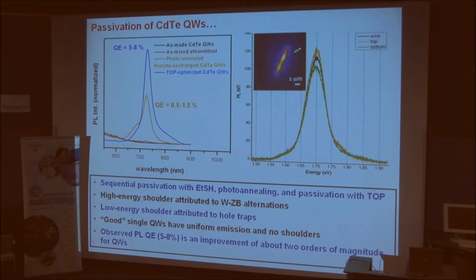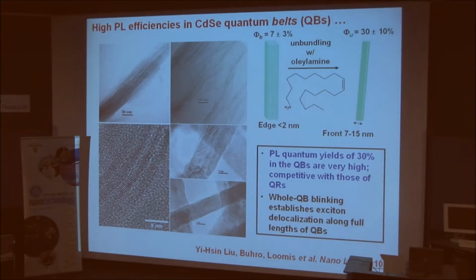And if we look at individual wires, we see that the well-behaved ones are uniformly bright, and they have uniform spectra all along the length of the wire. So these observed efficiencies in the range of 5 to 8% are an improvement of about 2 orders of magnitude over what's been published, and they're almost becoming respectable. Okay, now let me talk to you about quantum belts.